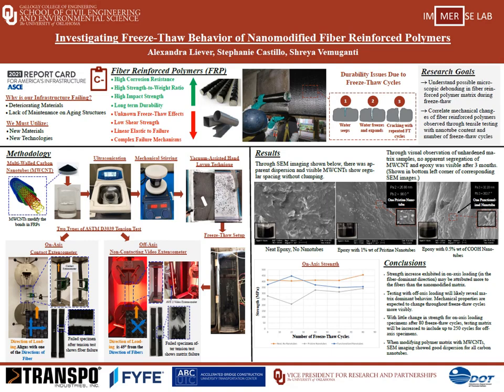In Oklahoma, there are around 60 freeze-thaw cycles per year. Once moisture seeps into the pores of the material, each cycle freezes the water, creating expansive forces and permanently damaging the material. One potential preventative measure for this damage is the addition of carbon nanotubes into the FRP matrix, which could help with bond strength.